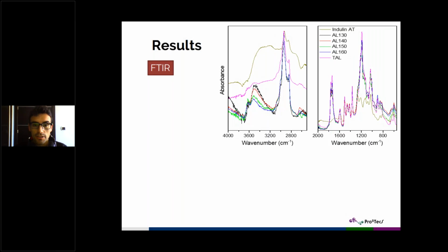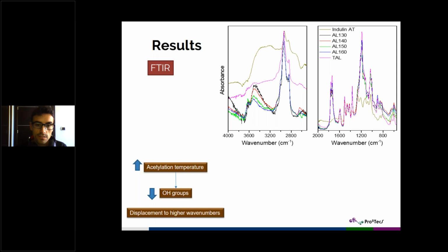Well, about the FTIR results, we can see on the left that the Indulin AT again shows a really high hydroxyl groups concentration. The conventional acetylated lignin shows almost no acetyl groups. And for the different temperatures, as we increase the acetylation temperature, we obtain again lower hydroxyl groups. That's just confirming what we saw in the NMR results. However, in this FTIR, we can also see that we are having a displacement to higher wave numbers when this acetylation temperature is increasing. What's that telling us?